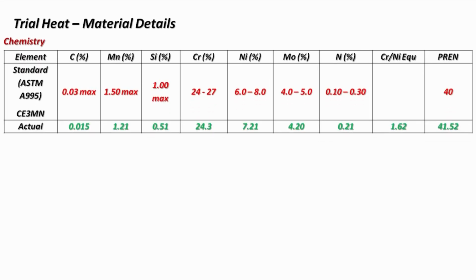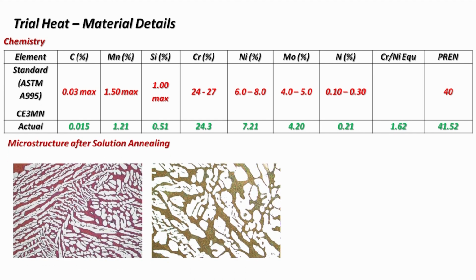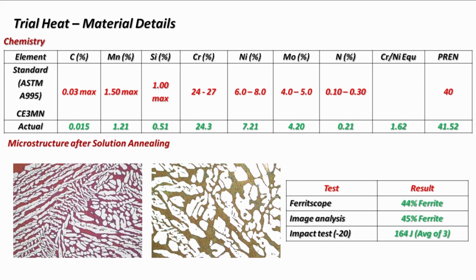Now the material details. The chemistry we maintained in the steel is shown here, and the PREN we got is 41.52. The microstructure of the material after solution annealing shows clean austenite and ferrite phases free of secondary phases. The ferritoscope shows 44% ferrite, and through image analysis we get 45% ferrite. The impact test done at minus 20 degrees Celsius showed 164 joules, average of 3 samples, and the material we took for the trial is grade 5A.